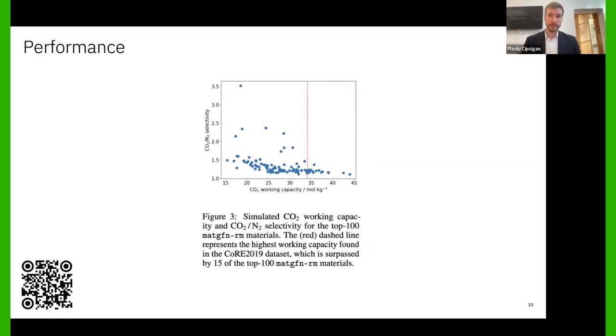We've also assessed the performance of these materials in terms of CO2 working capacity, which we know correlates with the surface area, and also CO2 N2 selectivity. So how much more CO2 it captures than nitrogen. The red line is the top CO2 working capacity in another reference data set, Core 2019. This is surpassed by 15 of the top 100 materials that we generate. So we generate novel materials and we also generate high performance materials. The CO2 selectivity is relatively poor for these materials, but it makes sense because this was not a generation target.